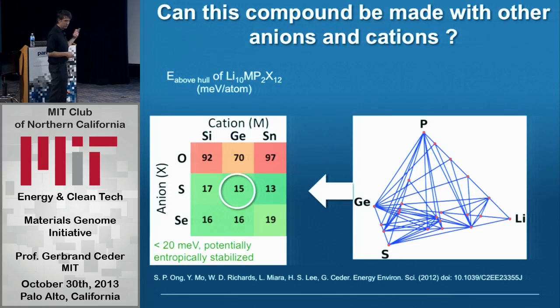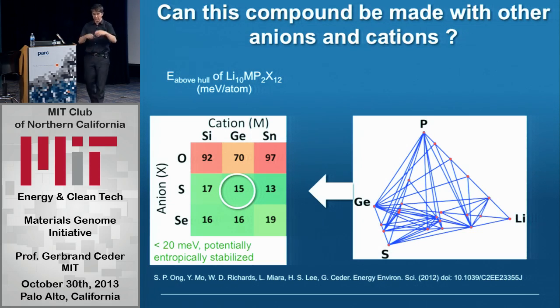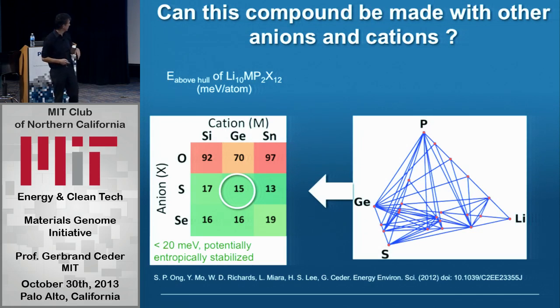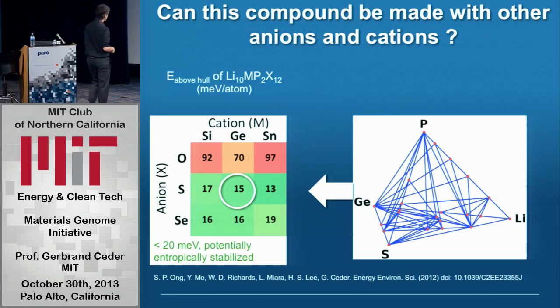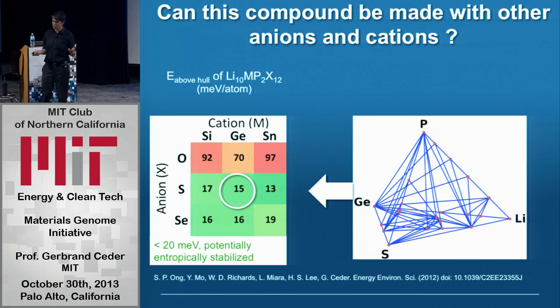First, we looked at where these materials are stable. This is where this high-throughput computing stuff would come in. And this is a bit technical. So what we actually calculate is, we do all the phase diagram calculations. We literally calculate hundreds of competing phases as possibilities. And we look at what the driving force is to go to other phases. And you want that as low as possible. Ideally, you want that 0. So the material you can make, LGPS, has a 15 milli-electron volt driving force, that's per atom, to go to another material. That's something we know we can manage.